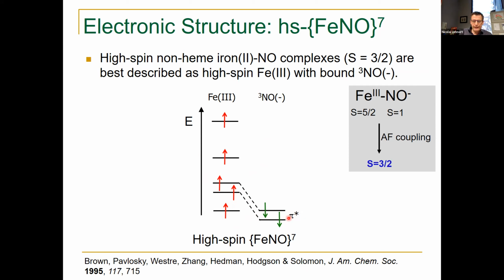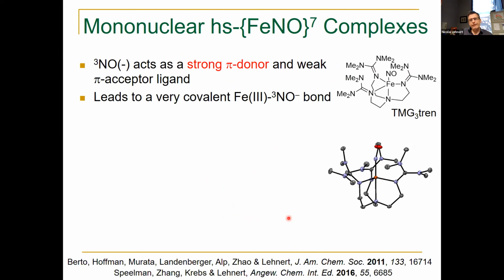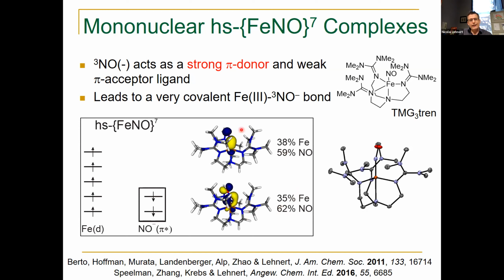We're looking at the bonding now, right? Advanced notation we already explained. What is the nature of this bond? This triplet NO- ligand is really mostly a strong pi donor ligand. And you can see this if you look at, for example, this DFT calculation here, you look at the pi star orbitals of the NO- ligand, you can see that they have about 35% iron character, right? So this is a very covalent, very strong interaction here at the center really of the bond.